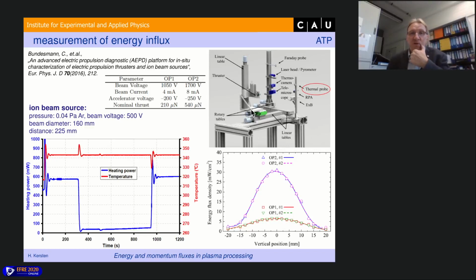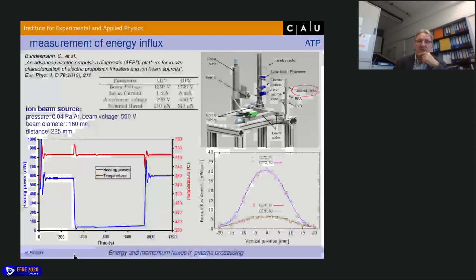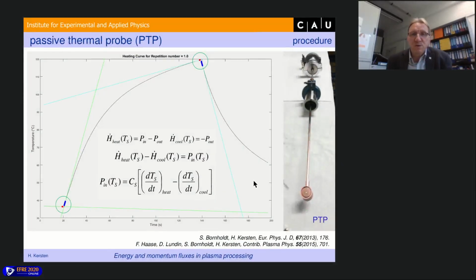So we had here a stage that was a project with the European Space Agency, and we had here the ion beam source, a thruster, and a lot of different diagnostics. And one of these diagnostics is here the active thermal probe. So we could measure the beam profile of the ion beam, as you can see here by this method, for different operation regimes. I will not go into detail, but you can measure here the integral energy flux by this very simple method. But mostly we use what I call the passive thermal probe, and this is even more simple.